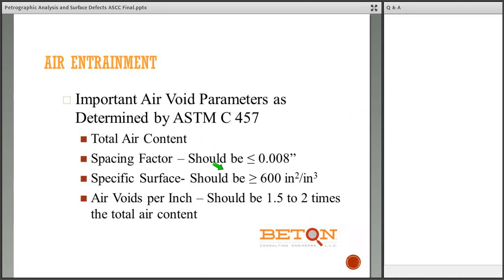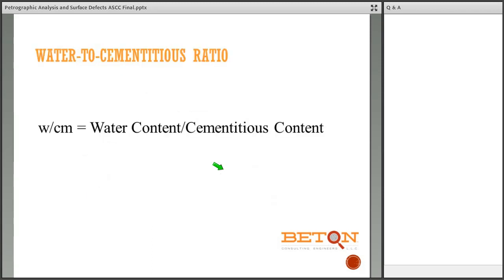Important air void parameters: total hardened air content, spacing factor should be 0.008 inches or less, and these are from ACI 201 recommendations. Of course, if you've had a chance to read Powers' original paper on it, he said 0.01 or thereabouts. Specific surface should be greater than 600 inches squared per cubic inch. Air voids per inch should be 1.5 to 2 times the total air content.